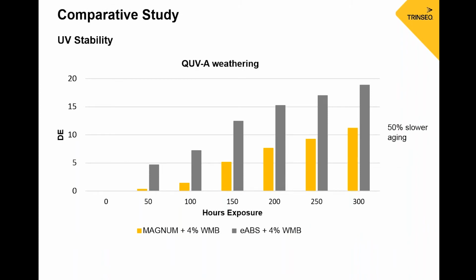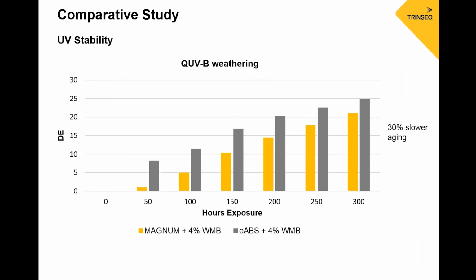So we also looked at weathering properties, and here we looked at QUVA weathering, and we measured the color change over time. This was with the 4% white master batch in each, so equivalent samples of the mass ABS and the emulsion ABS. What we could see here, we're calling this a 50% slower aging due to the color change difference that we see in these products. We also looked at QUVB weathering, and not quite as good of a difference, but still a pretty large difference of 30% slower aging based on the color change from 0 time to 300 hours.